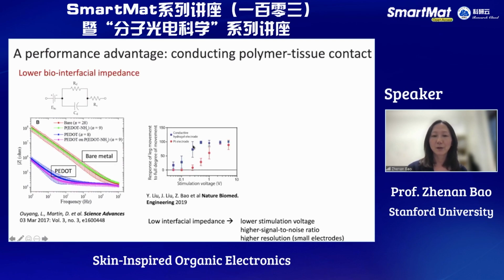This is what we have demonstrated with the conducting hydrogel that we developed, that's tissue level softness. And compared to platinum electrode, which is the red curve here, the y-axis is the amount of leg movement that's induced by electrical stimulation. And with the conducting hydrogel electrode, we can induce leg movement at 10 times lower voltage compared to that of the metal electrode. And then this lower voltage can really reduce the potential damage to the biological tissue.